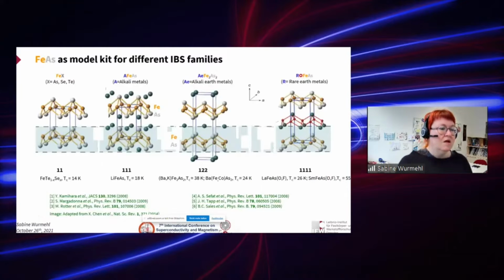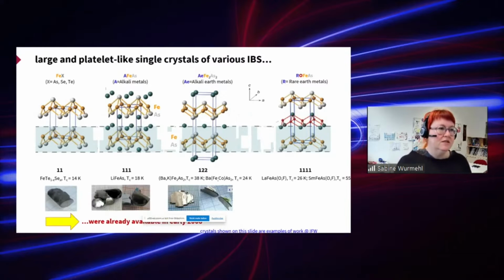There are very different families of iron pnictide superconductors, and they all share these iron arsenide layers as a building block within the structure. The families on the left-hand side, the 1-1, the 1-2-2, and the 1-1-1, were already grown as single crystals in early 2008, and then in-depth studies were soon reported on those materials.